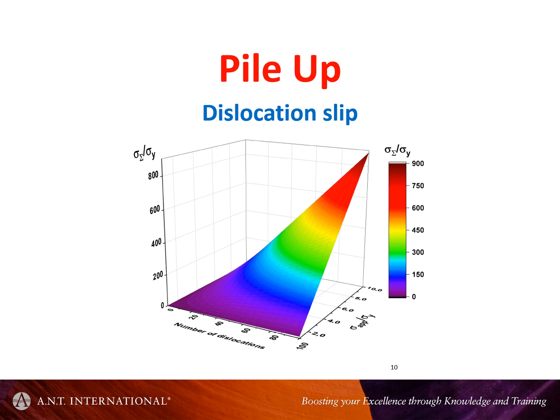So this brings us on to pileup, and pileup is a mechanism where the stress at the head of a dislocation, a series of dislocations that are following one another, when they hit a barrier and the lead dislocation is held up, there can be a situation where you can get some amplification of the stress because of the way that the dislocations interact. And this is just from a paper by a guy called Roman Voskoboynikov, and it just shows that if you have lots of dislocations and you have a very large difference between the applied stress and the stress necessary to move the dislocation, then you can get a significant amount of amplification.